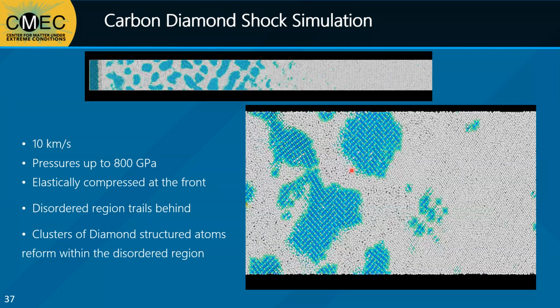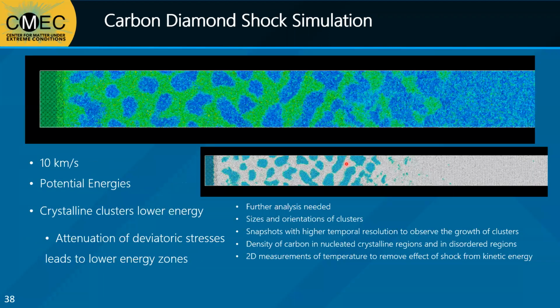A closer look at the transition from the ordered to the disordered zone sees the formation of separate clusters of diamonds surrounded by a disordered mass. These recrystallized areas appear to have a high concentration of twinning as well. When we do a potential energy analysis of these zones, it shows that the recrystallized zones have a significantly lower energy compared to that of the disordered regions. These recrystallized zones help to attenuate the deviatoric stress on the material, leading to lower energy zones.